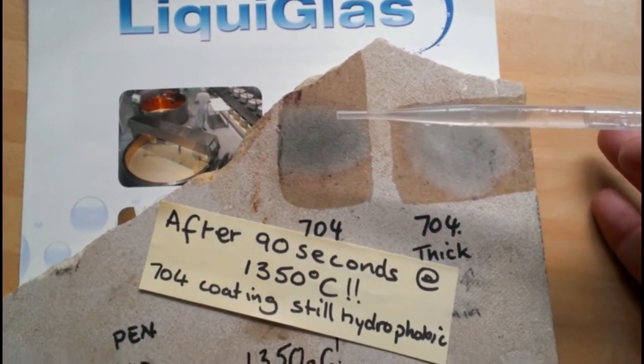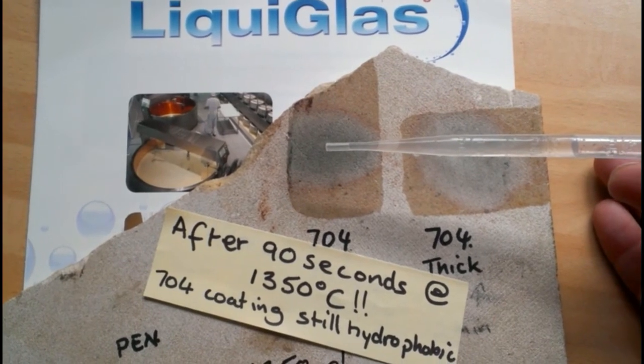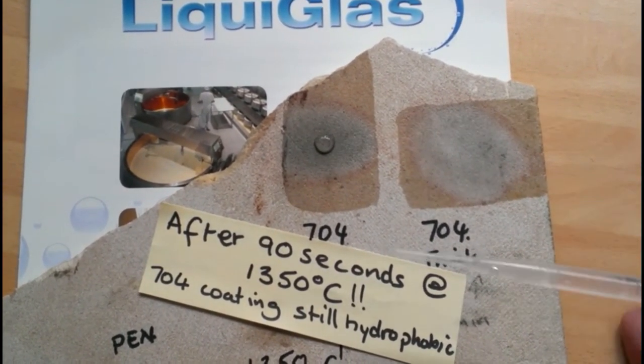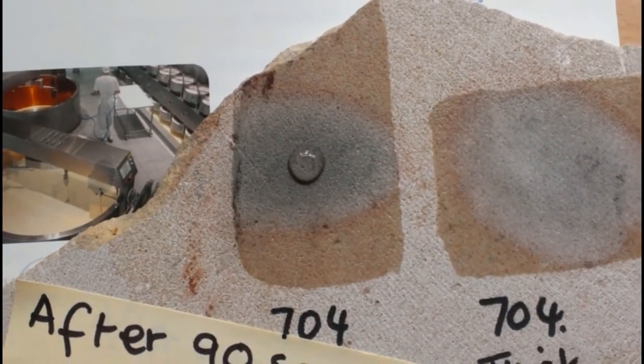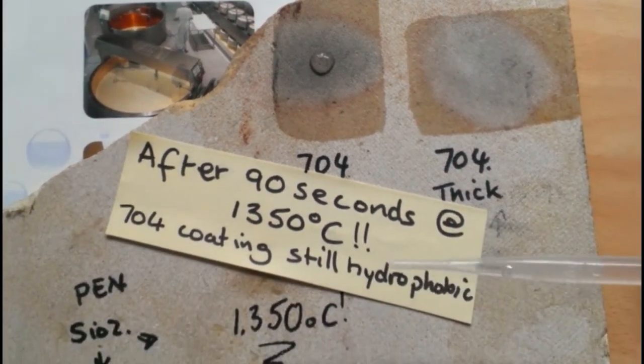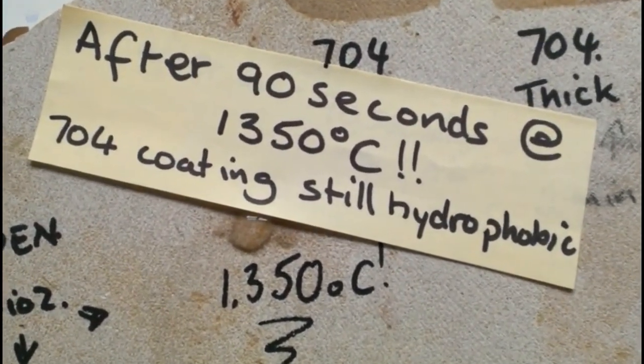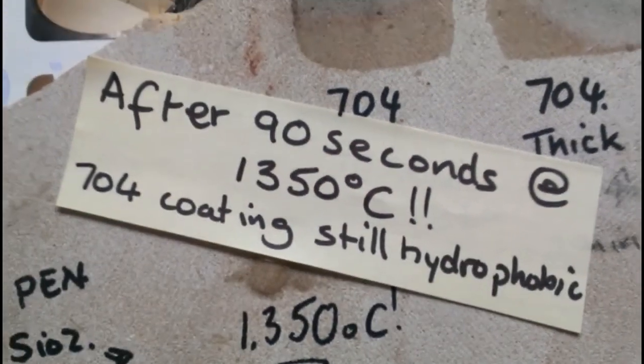We heated this area here to 1350 degrees Celsius, and we're now going to put a drop of water which shows that it is still strongly hydrophobic. No issues there. And then we're going to put some water here which will show that it is standard uncoated stone, non-hydrophobic.